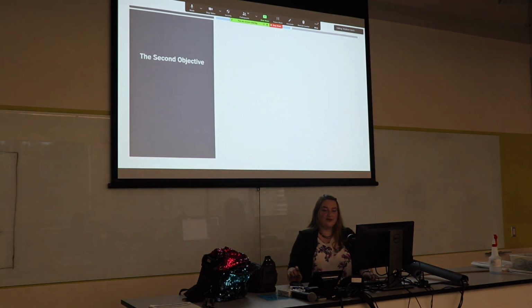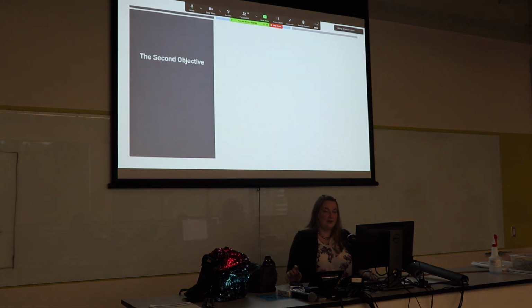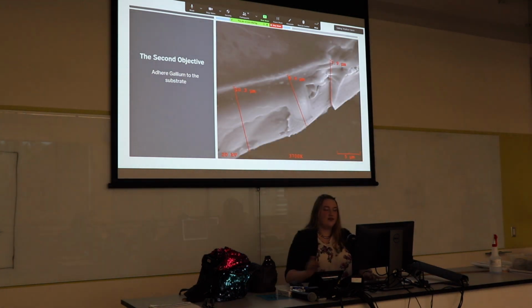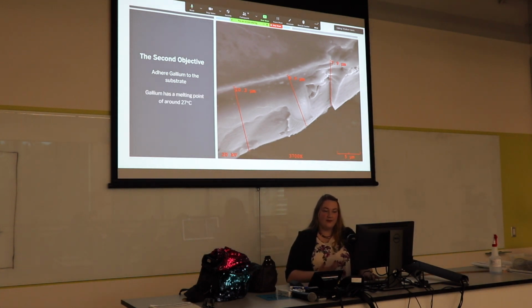Our next objective was to put the gallium on top of our silicon. Gallium has a very low melting point. It's around 27 degrees Celsius. You can just melt it in your hand. It might sting your hand a little bit, but it's relatively harmless. And you can see here that it has made a very even film on top of our substrate. You can see the gallium is coated evenly. We just warmed it up a little bit and then painted it on with a paintbrush.